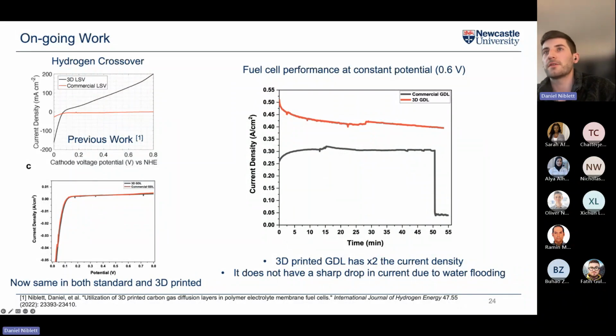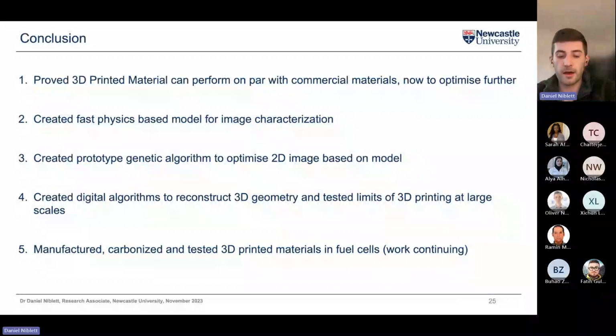And there's some indication that the 3D printed material may be performing better than the carbon paper, as shown by the image on the right here, which essentially shows at a constant potential, so 0.6 volts, what is the current density you get from the device. And the 3D printed material is almost double the commercial gas diffusion layer material. So it produces double the amount of reaction rate at the same potential. And it appears to not have as sharp of a drop in the current due to water flooding, which you see after 50 minutes. So there is some indication there that the material is performing better, but we still need to do more tests. And we should have a paper on this possibly out next year, but we need to get some more fuel cell testing done.